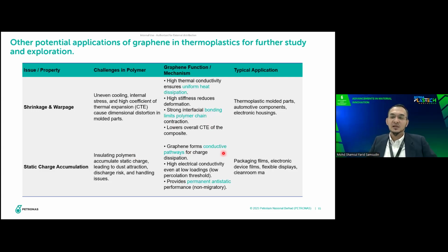And as for the anti-static application, definitely graphene gives very good conductivity at a certain loading. For example, in this case, 1 to 3 weight% can further improve the conductivity of the polymer, and from there it can work very well as a permanent anti-static additive in the film. And the target application for this anti-static is mainly packaging film and also electronic device material.